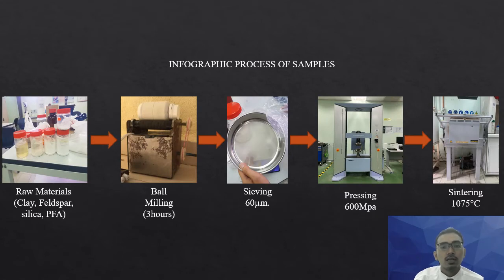For further understanding, I put an infographic for each process and the equipment used. The first one is the collection of raw material, which is the clay, feldspar, silica, and pore forming agent. Followed by the ball milling process for 3 hours, then the sieving process to differentiate the granulate powder and the fine grain powder. Next is to use the pressing machine to press the powder into the molding samples. And the samples will be brought into the furnace for the sintering process at 1075 degrees Celsius, and finally the material will be cooled down before proceeding with testing.